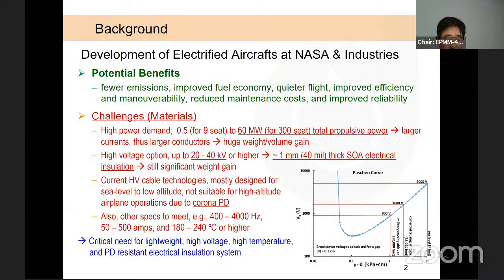conductors, and that would result in huge weight and volume increase, even though heavy mechanical and pneumatic machineries would be removed. One solution to avoid the larger conductors for reasonable weight management was to use a high voltage, but then it would require much thicker insulation with any state-of-the-art system, again significant weight gain. On top of that, current high voltage cable technologies mostly developed for sea level were not suitable for the high altitude applications due to higher corona susceptibility.